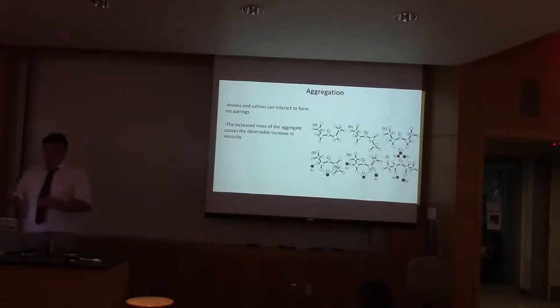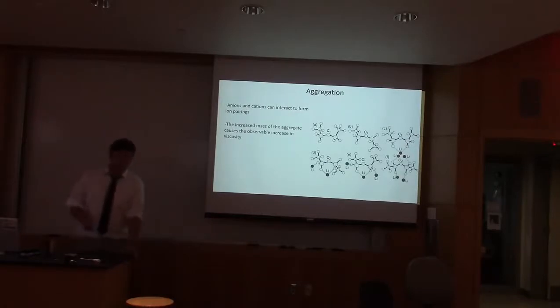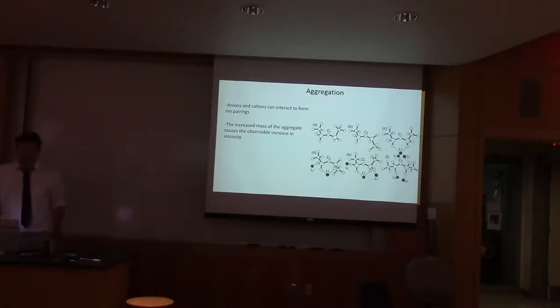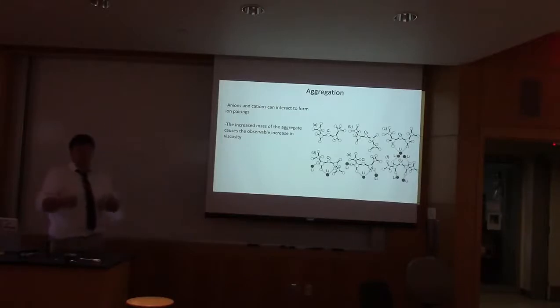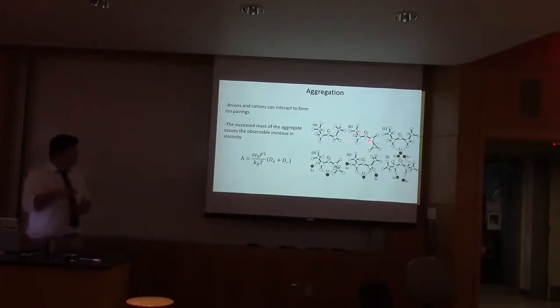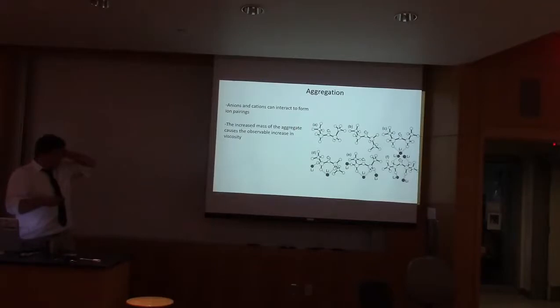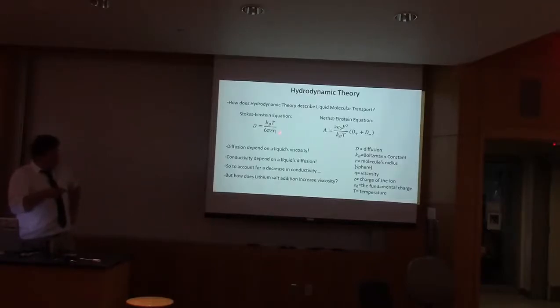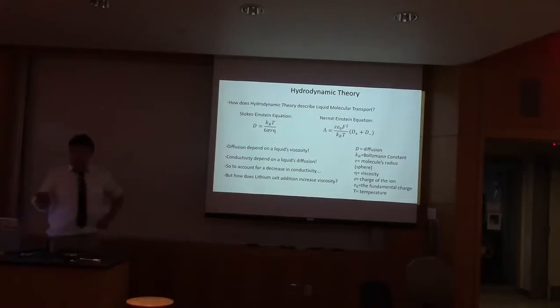The increased mass caused by the aggregation of lithium, since it's such a charged and small ion, causes the observed increase in viscosity. Basically, we have a larger molecule because it's aggregated, and it's harder to move that through a liquid because it's so much more mass. That's hydrodynamic theory's explanation for our observation in the increase in viscosity. And as we can see, if we go briefly back to the other slide, as we increase viscosity, we decrease the diffusion, and a decrease in the diffusion for both the cation and the anion will result in a decrease in the conductivity.